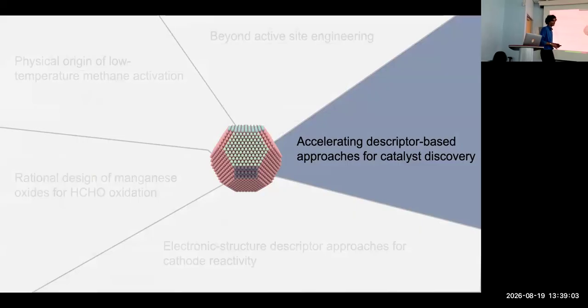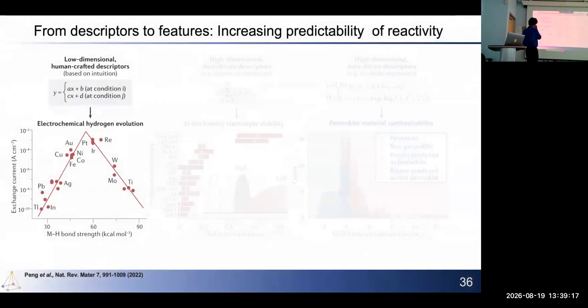Now the question is how do we reconcile this simple intuition-based methodology with accelerated machine learning models that are complex by definition? Here's an example of what we've been looking at: you have an experimentally measured activity metric — reactivity, turnover frequencies, kinetic rates — and a descriptor on the x-axis that was easy to explain. We've been developing these linear models to explain why, for example, something would show up at the peak of this trend.